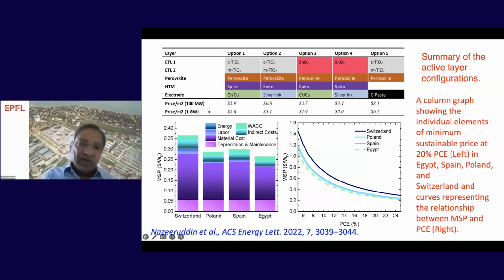If we start at gigawatt scale, this will be around $5 per square meter. That's a pure material cost. But of course, there are two glass plates, which will be around $12. So these are the typical costs of one square meter perovskite panels. Now, if you take option two, where we again have a compact layer of TiO2 followed by mesoporous TiO2, perovskite, spiro, and silver as an ink, the cost is close to $7 per square meter for material.